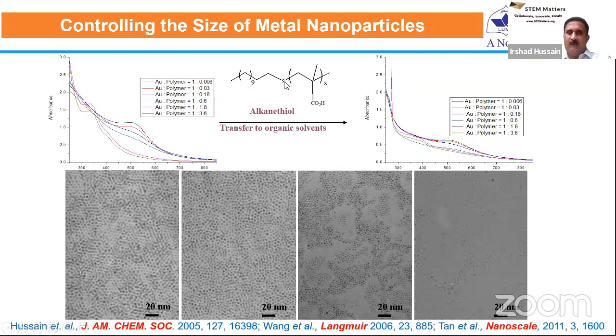And remember, this thioether interaction with gold particles is slightly weaker. It can easily be replaced with alkane thiol molecules, and you can then transfer these particles from aqueous media to organic solvents. If you carefully note the structure of this thioether polymer, it has carboxylate functional groups, and due to this, these particles are soluble in water. But you can tune their solubility and transfer them to organic solvent if you replace these ligands with alkane thiol molecules. And again, they will retain almost the same optical properties.